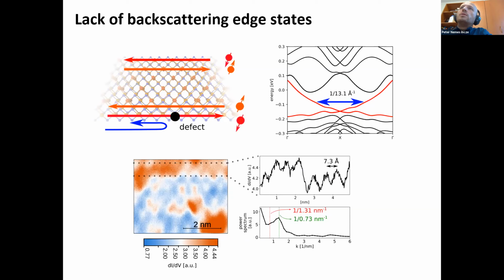So what you can do is you can look for what kind of standing wave wavelength we expect based on the dispersion of the topological edge states along the edge. And here I've shown at the energy we've measured, so in the middle of the band gap, you would expect basically a wavelength of these standing waves of the order of 13 angstroms.